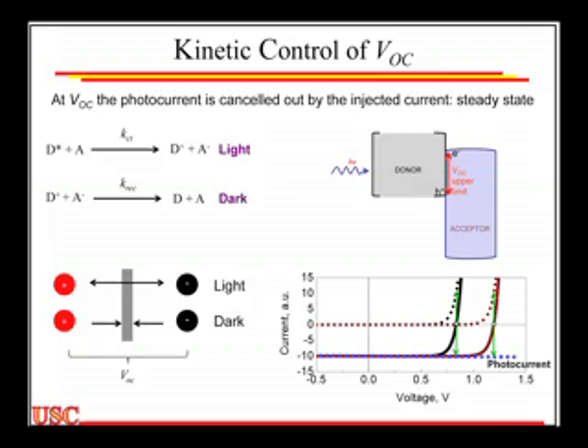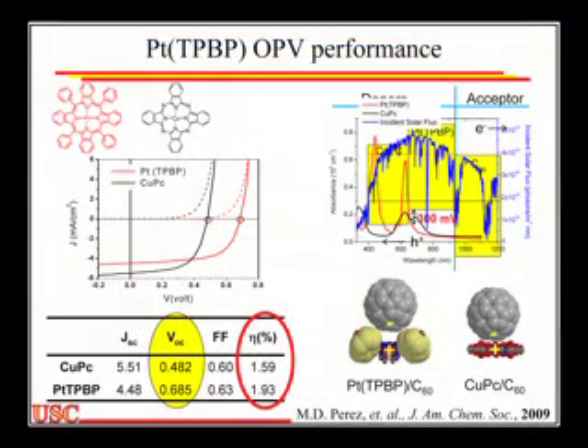So anything I can do to slow down this back reaction, anything that slows down this dark reaction, the reaction that would occur in the dark, will increase my open circuit voltage, because it will decrease my dark current. If I go back and look at the molecules, the ChemDraw pictures don't tell you the story at all, because they suggest that the structures of these two are quite similar, and they're not similar at all. This is a side view of the copper phthalocyanine, and this is a side view of the tetrabenzoporphyrin. The phenyl groups in this case are flanking it, and in fact the porphyrin molecule itself looks like a Pringles potato chip. It's not at all flat.